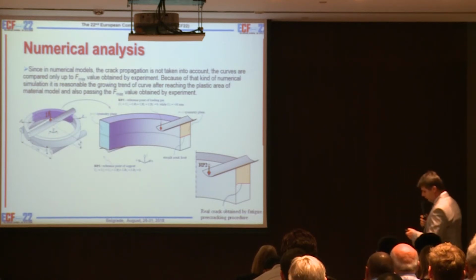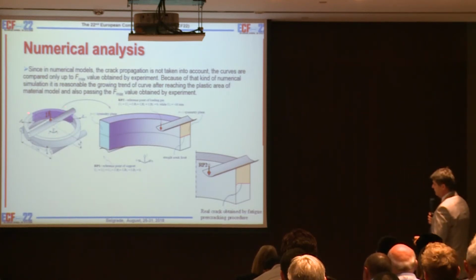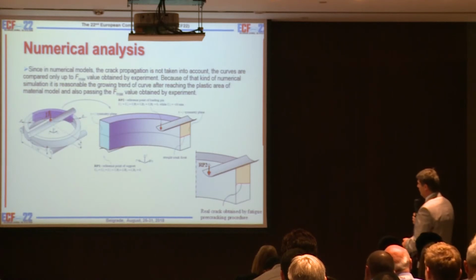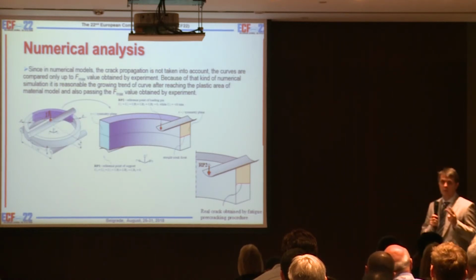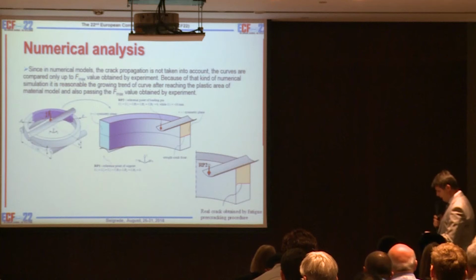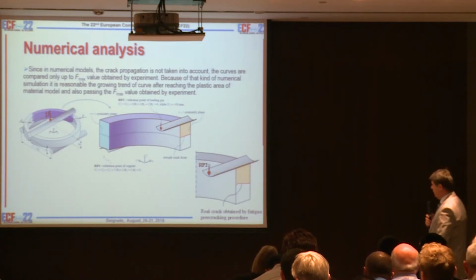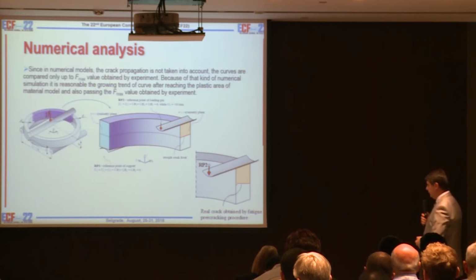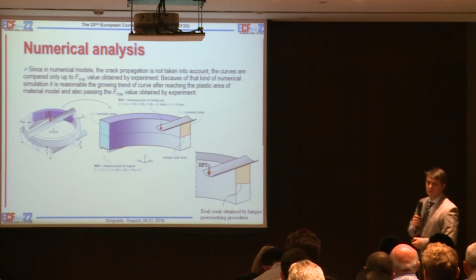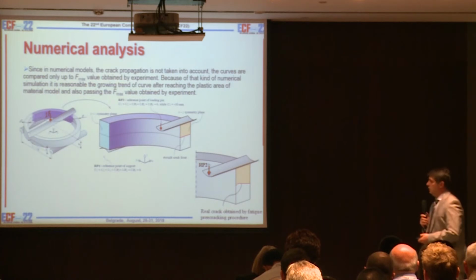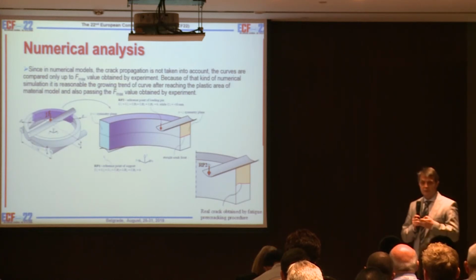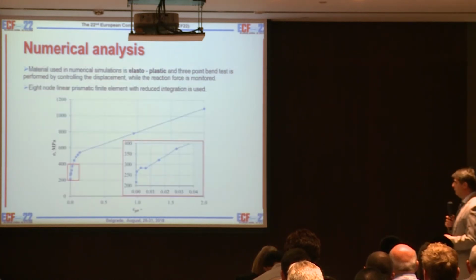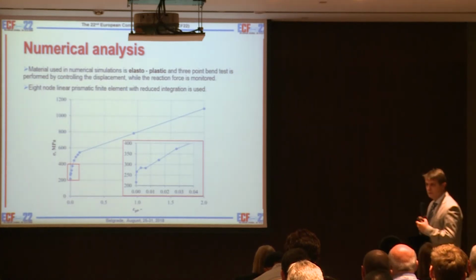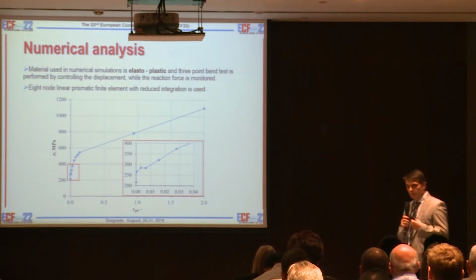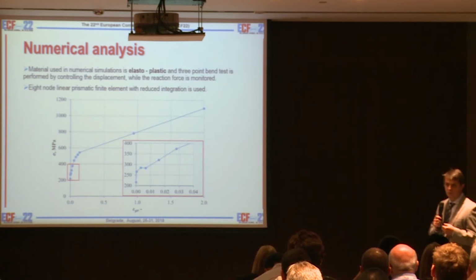In order to do this, we make the model. We use a quarter of the specimen, like here, this color, and we consider two kinds of notches. One is the straight notch, you can see here, with a straight fatigue front. It's not realistic, and one is a realistic uneven fatigue crack front. So why? Because we want to see what is the difference in these values, and then we can see if these differences make this specimen useful.